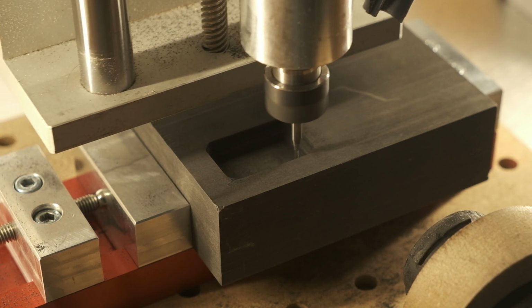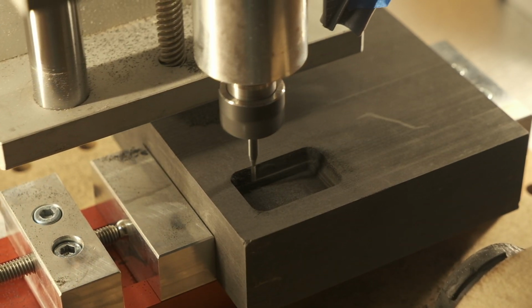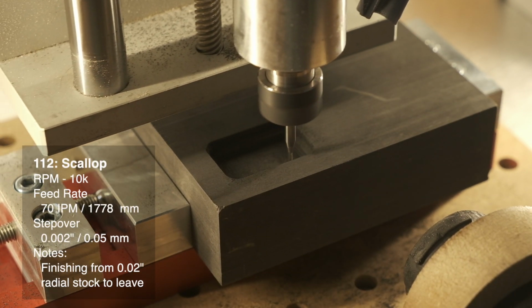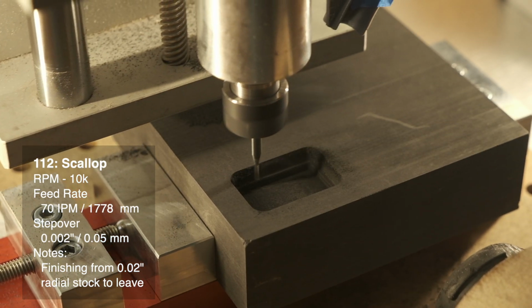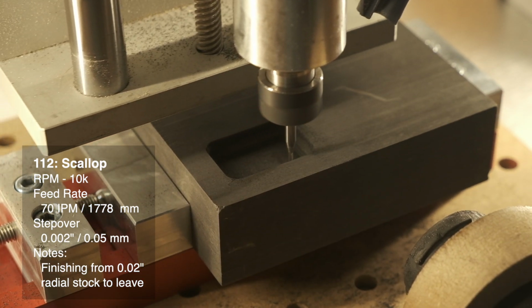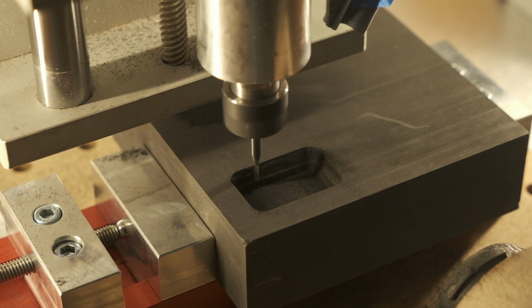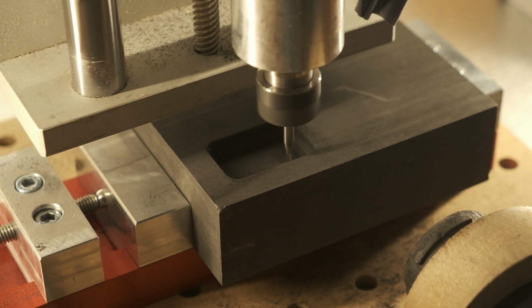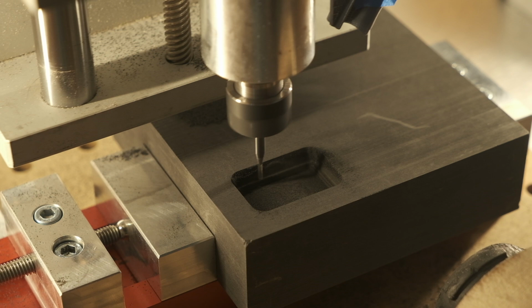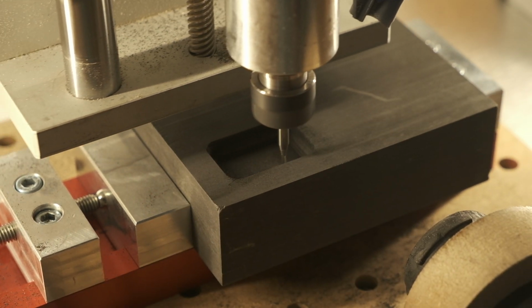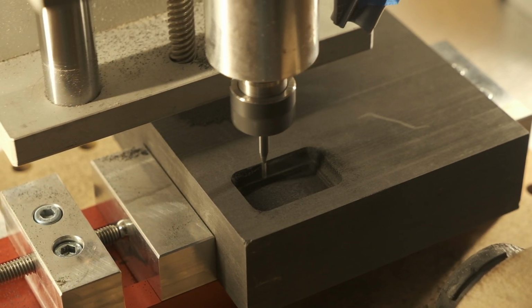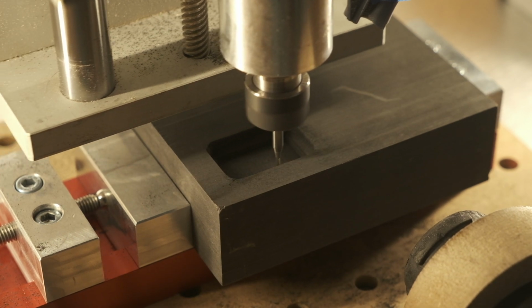Next up was a scallop finishing toolpath with a 1/16 inch ball end mill. 10,000 RPM, 70 inches per minute with a 2 thou step over. Now, keep in mind, our cutter engagement is not 100% here. We should hopefully be running into graphite with at most a third of our cutter. And our stepover is really small for resolution purposes. This is a finishing toolpath, not a roughing toolpath.